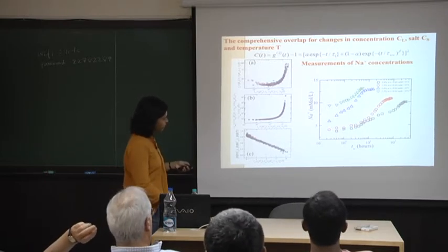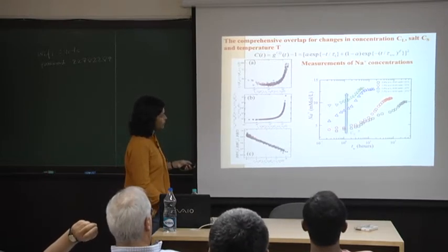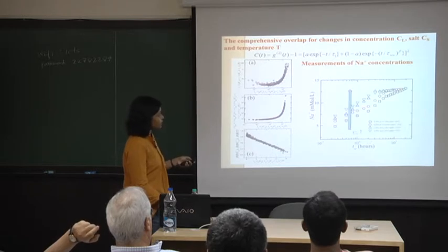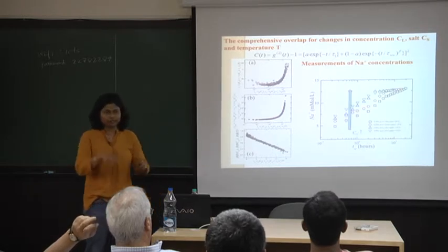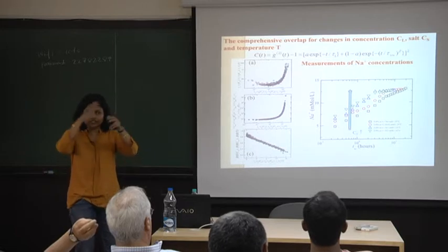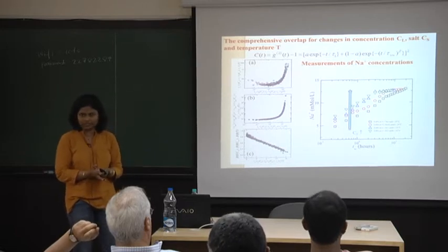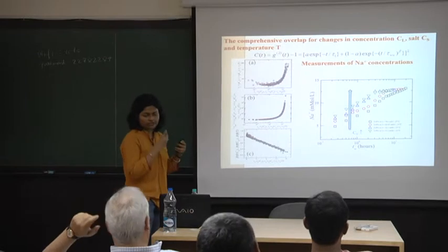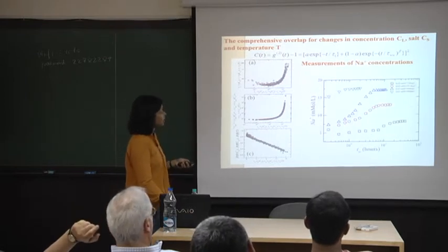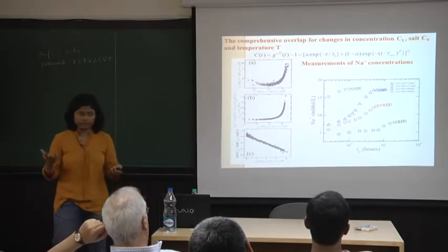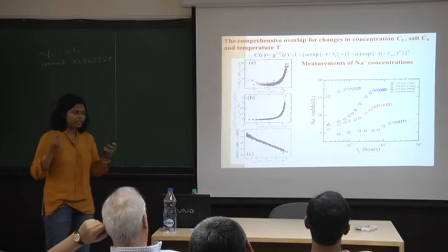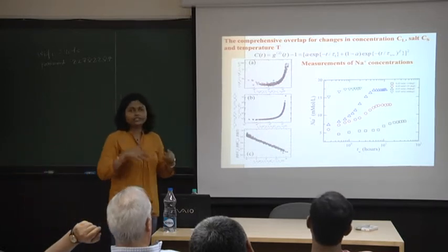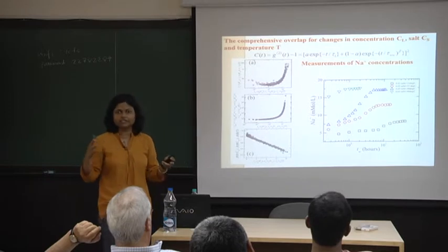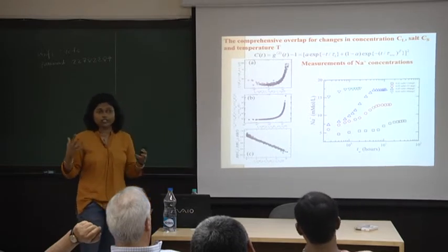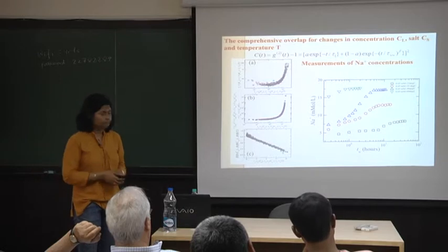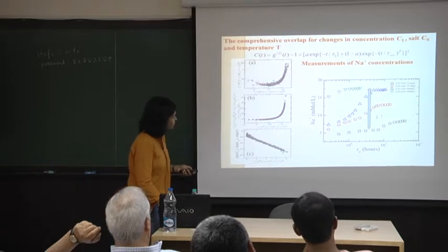This is for our data where the concentration of the Laponite particles was increasing. This is data where the salt is increasing, so you basically just put in some more sodium chloride, you're screening the Debye layers around the particles, and you're measuring the number of sodium ions in solution. You're doing the same thing when you increase the temperature. So temperature does the same thing. The effect that increasing the temperature has on the suspension is that it increases the number of sodium ions in the solution. Okay? So that's exactly what we've measured here.